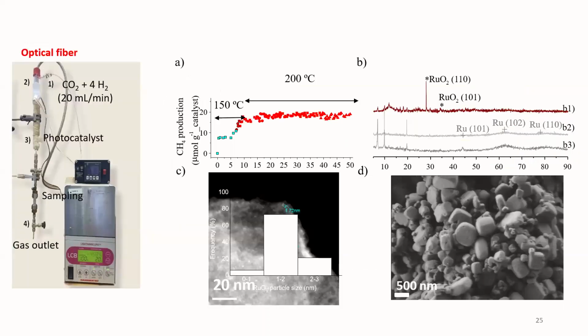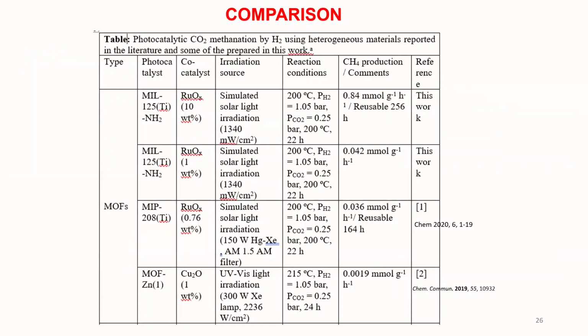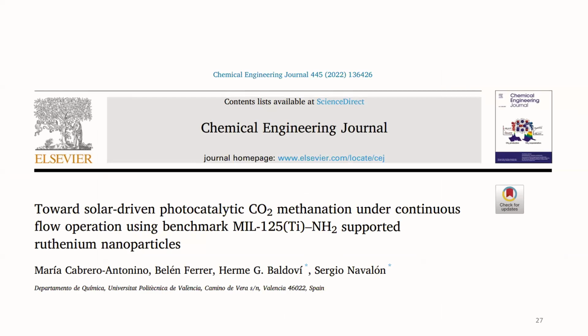Finally, we also wanted to check a continuous flow experiment with this. We developed an in situ photoreactor where we introduced CO2 and hydrogen. This is the concentration, and we put in this catalyst, ruthenium loaded on MIL-125 amino, and connected it to a micro GC, and we continuously monitored the formation of methane. At 150 degrees and at 200 degrees centigrade, the activity was more or less good. This is the XRD of the fresh and reused catalyst, and the stability was also confirmed by TEM analysis. This is the comparison table, and this was published in Chemical Engineering Journal.